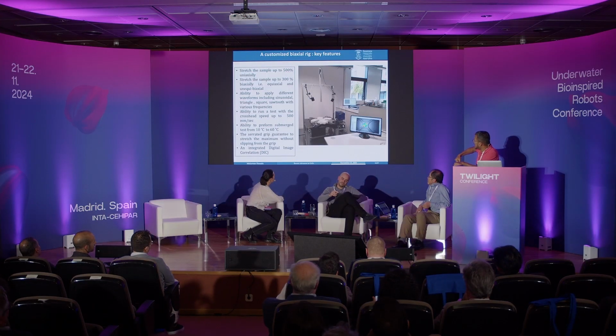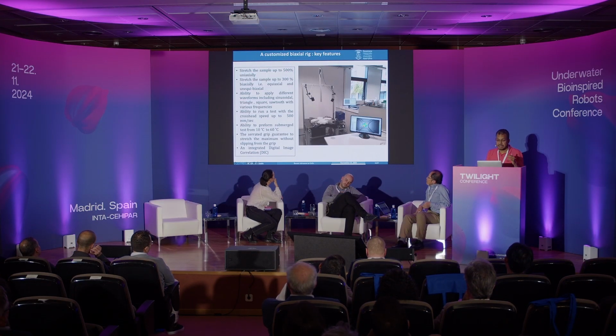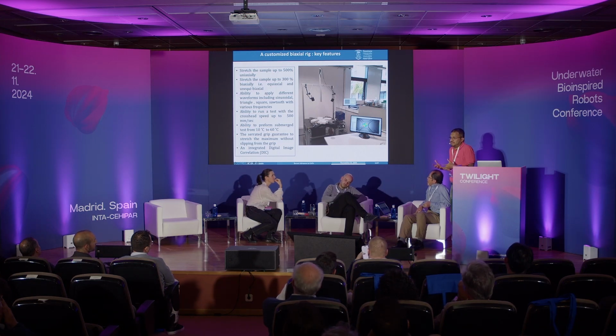So I was lucky to get some funding a couple of years ago to develop a customized system that can do multi-axial fatigue tests. And this is the machine. You can see this is a really, really customized machine for soft material. You can put the sample underwater. So this is the DIC underwater, so you can track the deformation underwater. And the water temperature you can change if you want. So we can go up to 60 or 80 degrees centigrade. We have a recirculating system, and it can keep the temperature constant. But the most important thing is you can deform the sample up to 500% deformation, okay?